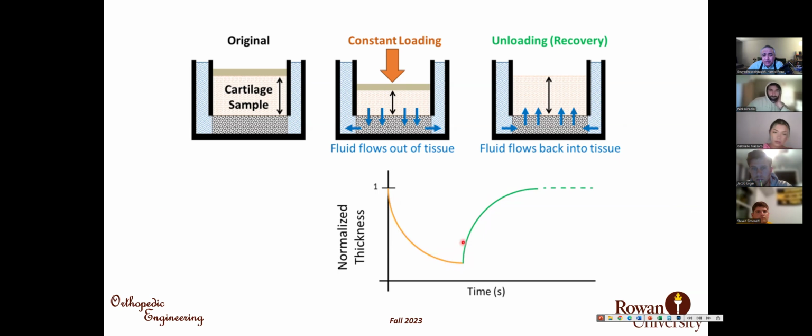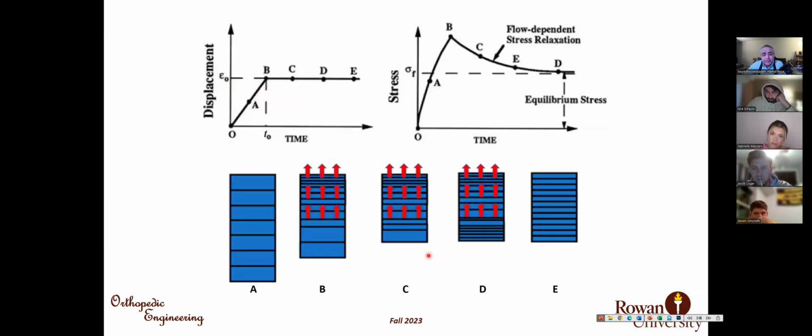So this gradual change is important for us, and it prevents sudden changes in the shape of the cartilage in our joints. How does this happen? In the first slide, I said cartilage has several layers. When we apply the load, the superficial layers toward the joint cavity first lose the water and they are compressed. And the deeper layers try to distribute their water between the other layers. And this gradually continues until all the layers have equal distribution of water loss.